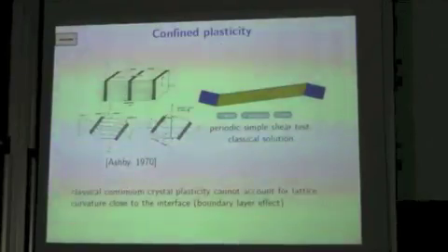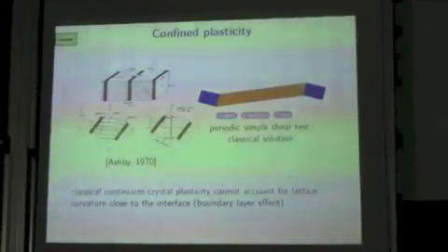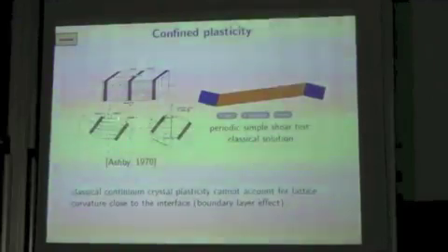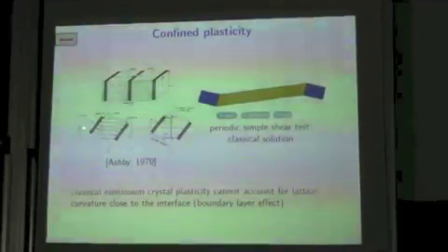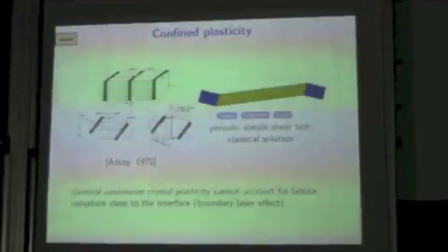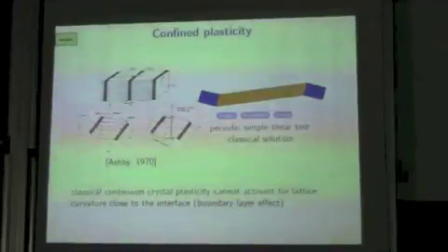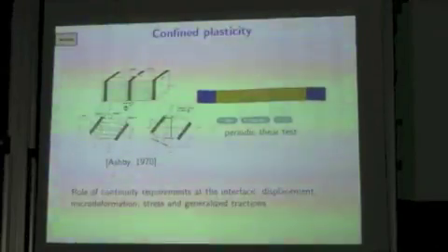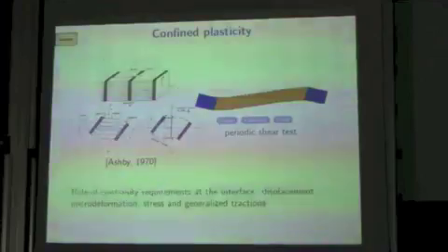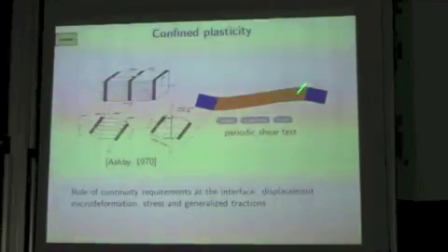The classical solution is homogeneous strain in each phase, which does not look like the picture of Ashby, where you have some curvature of the lattice planes if the distance between the two elastic parts here is small enough. You can recover this by means of the micromorphic model, where you have these pileups of dislocations at the boundary.